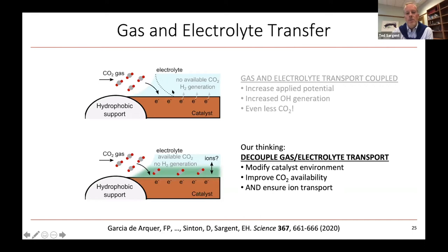But then as we try to penetrate further into the liquid electrolyte, the CO2 will rapidly turn to carbonate, which comes with a number of problems, but one of them is CO2 availability right near the catalyst surface over here. And this can easily happen in some of the electrolytes we use after 100 or 200 nanometers. So it's a real problem, especially if you're trying to build a kind of nanostructured or bulk heterojunction catalyst. So our thought was, could we add some kind of transport material shown here in the green? At the moment, it's kind of hypothetical. We'll tell you how we did it in a sec.